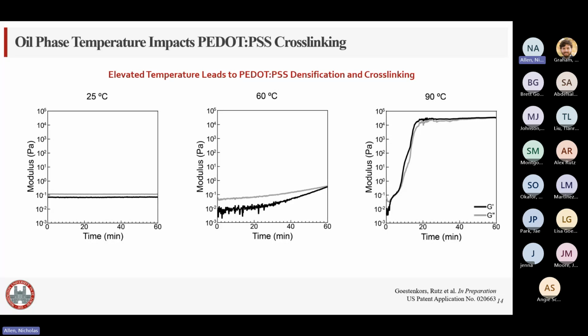The gray trend line is called the loss modulus, and the black trend line is called the storage modulus. And in rheology, when the loss modulus is higher than the storage modulus, it's indicative that the material you're testing has a more viscous, liquid-like nature, flowing more like a liquid. When those moduli reverse, it is indicative that the material is cross-linking and now is behaving in an elastic, solid-like nature.